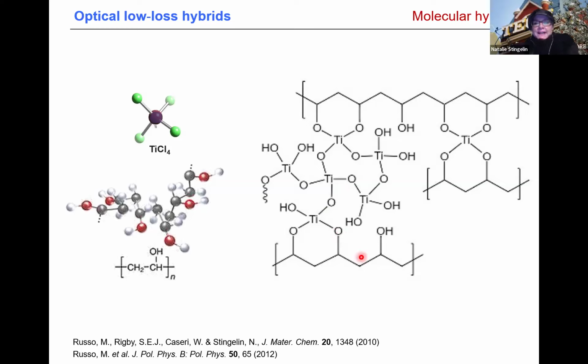So you get an amorphous material of inorganic macromolecules that are stabilized by these carbon chains, the polyvinyl alcohol. For this talk, not that important, but we think titania reacts with polyvinyl alcohol so well because it forms these bidentate structures, meaning titania grabs two hydroxyls that are next to each other, and therefore PVA is so good.